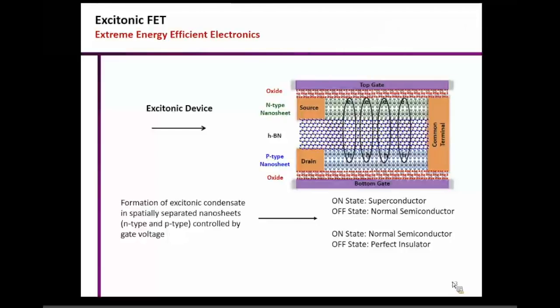This is something that we kind of propose: if you have an n-type 2D material and a p-type 2D material, but they are separated by a very thin gap. This has to be very thin because Coulomb force drops as 1 by r squared. So if you make this distance very large, then you are not going to have a lot of attraction between the electron and holes. But at the same time, you cannot make it very thin, because if it's too thin, then the electron and holes are going to tunnel through, and the wave functions are going to overlap, and it's going to lose this excitonic state.